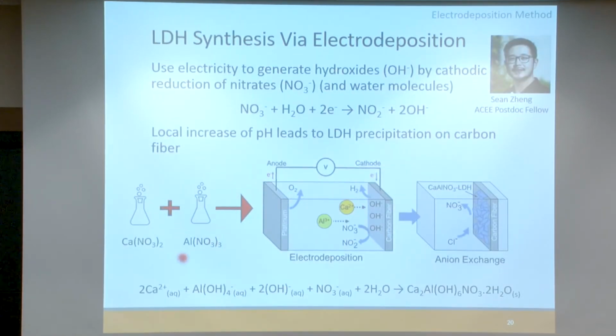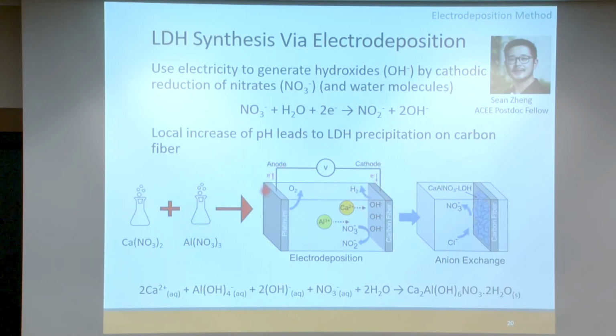The electrolyte is a mix of calcium nitrate and aluminium nitrate. And then if you apply a voltage across the electrodes, you're driving electrons onto the carbon fiber, which is now known as the working electrode, and you have this counter electrode being the platinum. Now what happens near the working electrode, this carbon fiber, is you get reduction of nitrate, whereby you're changing the oxidation state of the nitrate, but you're producing hydroxide molecules, hydroxide ions.